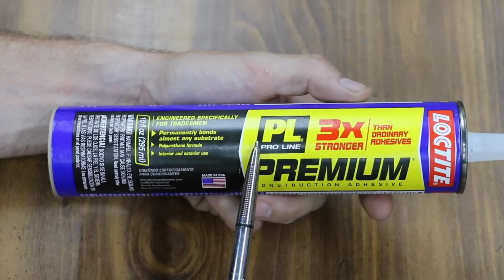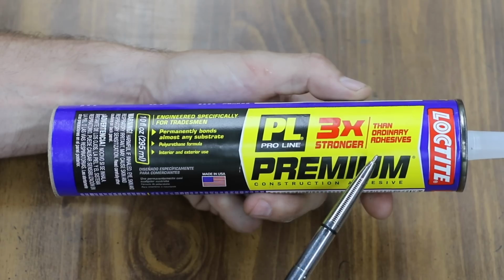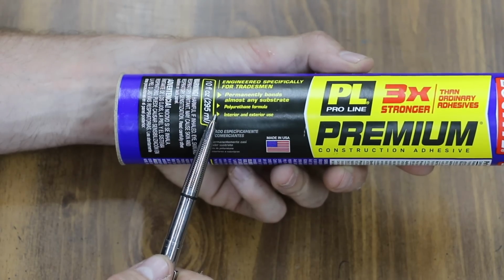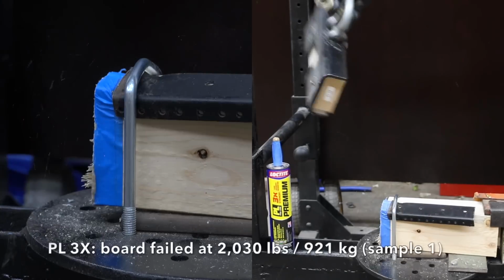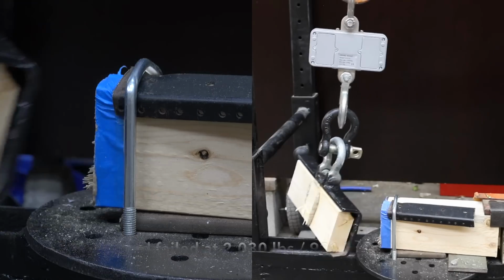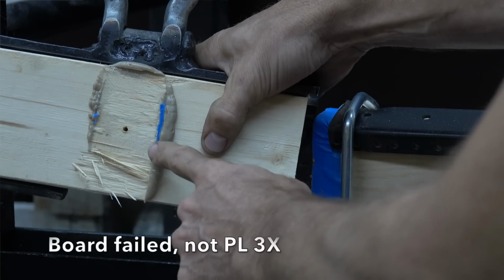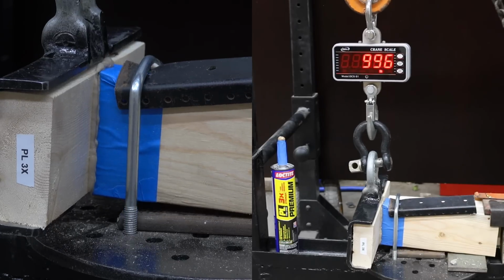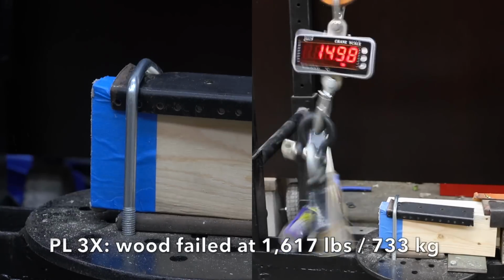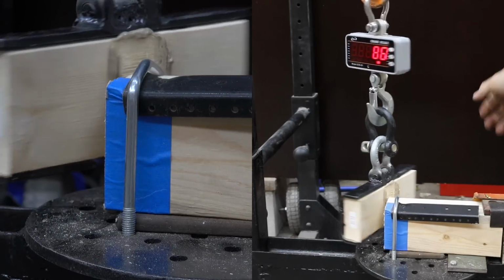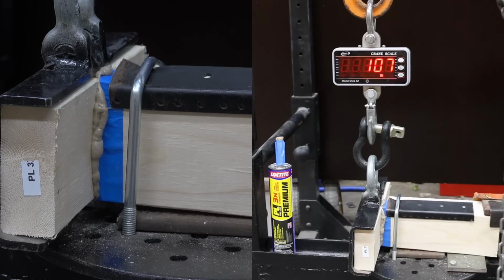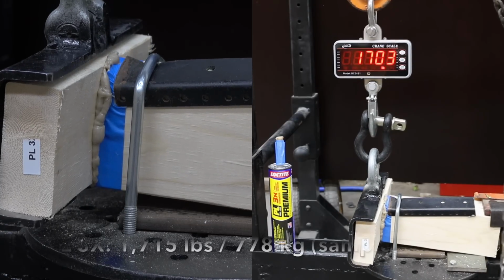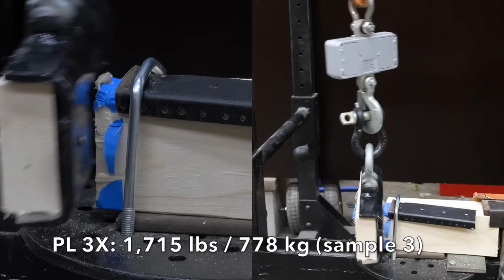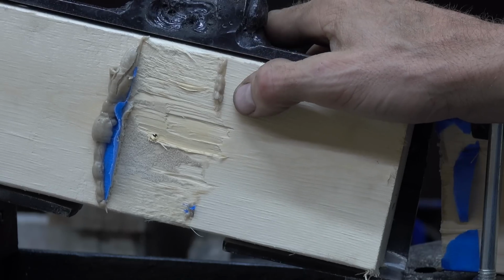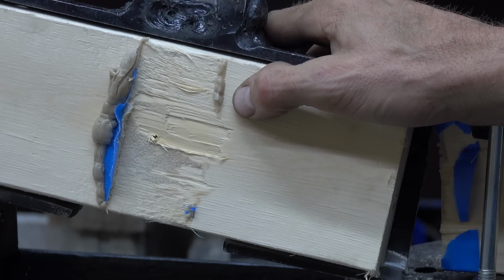We'll also be testing Loctite PL3X, which is supposed to be 3 times stronger than ordinary adhesive. It's a polyurethane formula. It's for interior and exterior use. Loctite PL3X did an amazing job at 2,030 on the first sample. Very impressive. Okay, over 2,000 pounds with the PL3X. The second was down a little to 1,617. The wood failed, not the glue. The third was 1,715, so PL3X delivered consistently good results. So PL3X is a very strong construction adhesive, definitely stronger than the wood. This product is pretty impressive.